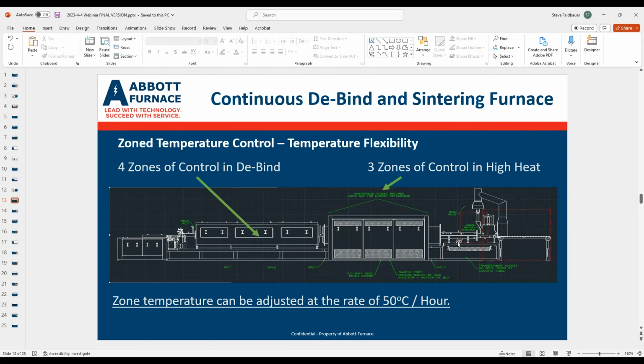So that being said, because you've got roughly a 120-inch preheat and 115-inch high heat, that gives you plenty of time to actually start loading your new product in while changing, and you're only going to lose roughly, you figure about 15 boats of product, and then it'll continue on. So you can actually change while you're processing. So it's actually very flexible. You would not be able to change that quickly in the case of a batch furnace.